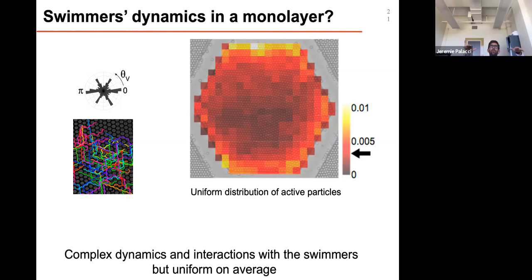So the slanted walls allow the active particles to escape and to come in, but the presence of walls on the other end doesn't allow the passive ones to escape. So the passive particles are confined, but the active ones are basically in an infinite bath, an infinite reservoir of active particles. And by doing so, we can ensure that the amount of active particles remains constant through the course of the experiment. And that's what this picture shows. And that allows us to say, okay, let's step back and take a mean field approach.